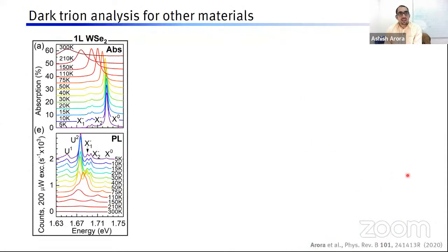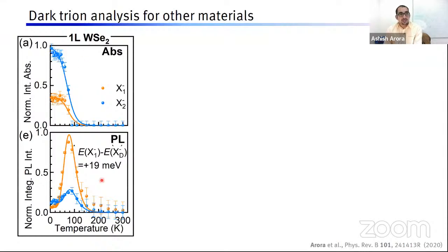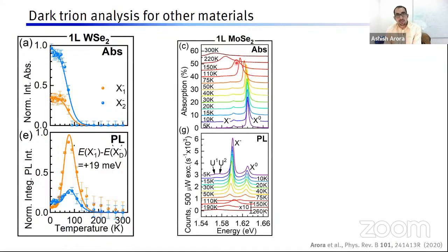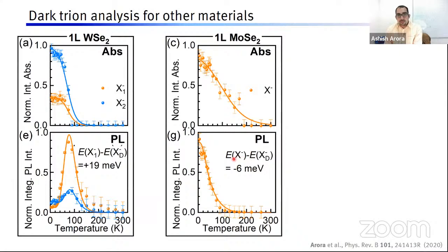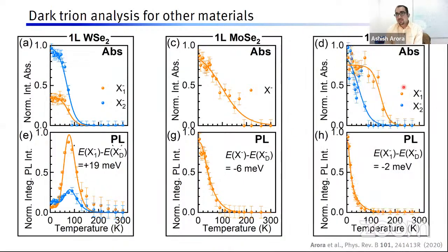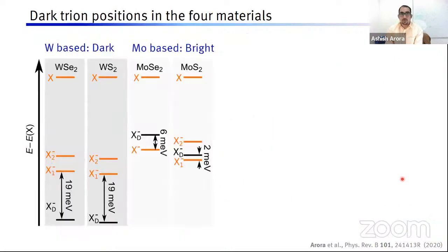We then do this analysis on other materials. In tungsten diselenide, we find that, similar to the disulfide, we have the dark trion, which is the lowest in energy by 19 meV. For MoSe2, the lowest ground state is actually a bright state by 6 meV. The dark state is 6 meV above the bright state, whereas in MoS2, the dark and bright states almost coincide in energy, within 2 meV.